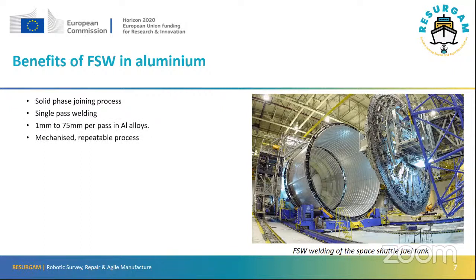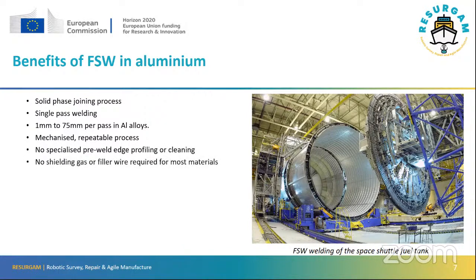It's mechanized, it's repeatable, so you always get the same quality of result. We don't need to do any specialized edge profiling or cleaning of the metal before we join it. We don't use a shielding gas or a filler wire for joining aluminium, so you've got cost savings involved. We get very, very little distortion or shrinkage. We're not melting anything. We're not putting a lot of heat there, so we don't get much distortion. We can weld in any position, vertically, overhead if necessary.